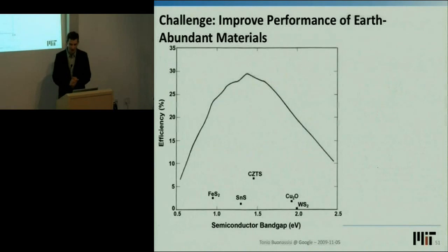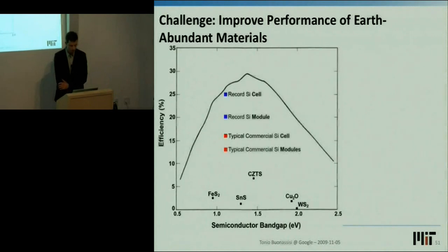However, if we start comparing the real efficiencies, the record efficiencies of these materials versus the theoretical maximum, shown here, this plot is the theoretical maximum efficiency as a function of band gap. And we compare the actual record solar cell efficiencies for several compounds, including iron sulfide, tin sulfide, copper zinc tin sulfide, cuprous oxide, and tungsten sulfide. We see that the record efficiencies of these earth-abundant compounds are much, much lower than the theoretical maximum efficiency. And this is after several years of work, especially during the 1980s, on these particular compounds.